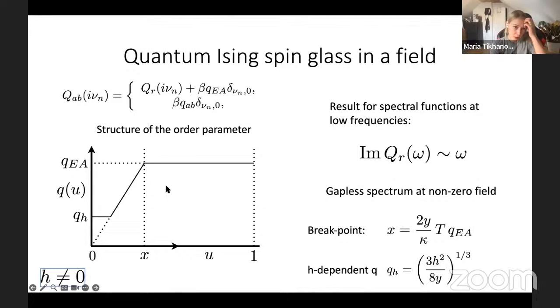Now this X where this cusp is happening is called the breakpoint, and it's an important value because it depends on the temperature. So that will dictate whether you go to lower temperatures where the structure becomes more like an order parameter, whereas at high temperatures, in order to reach the order parameter, your infinite step replica symmetry breaking occupies a lot. In this QH, we also can find an analytical form. So it depends on the longitudinal field.